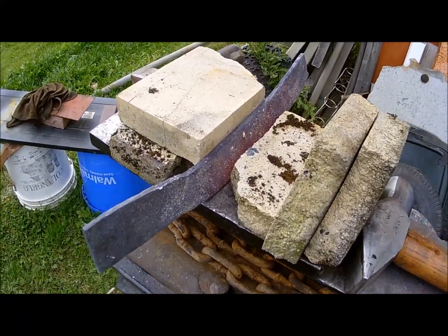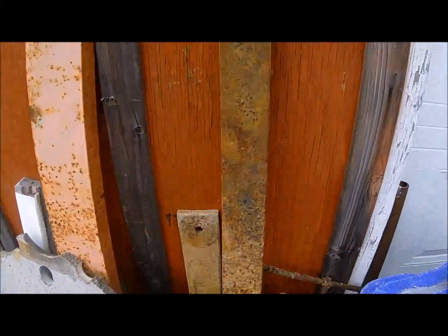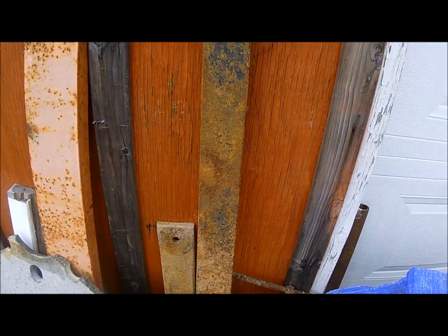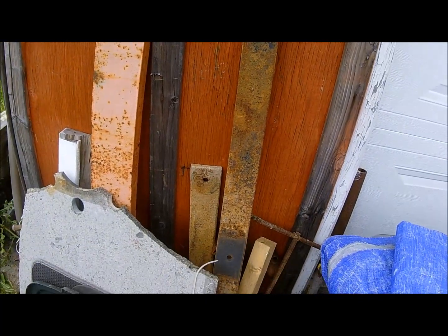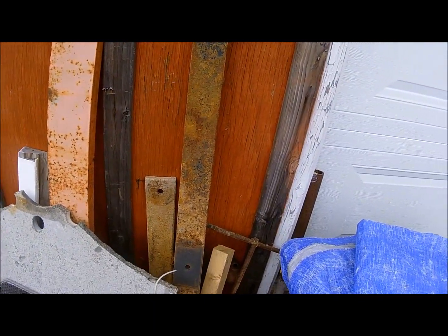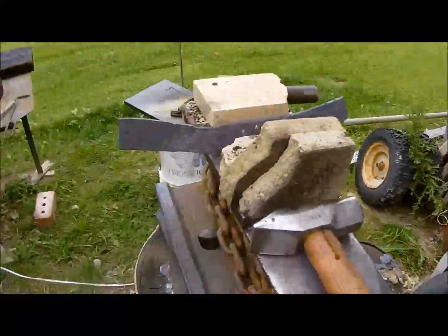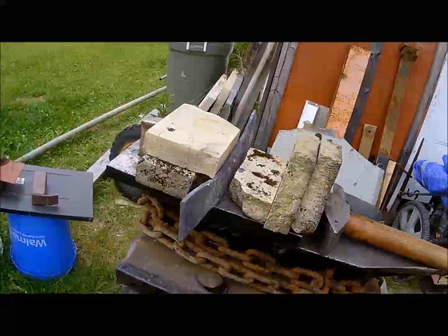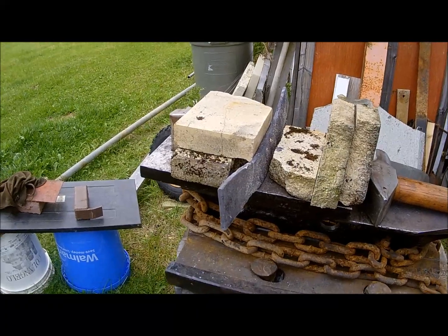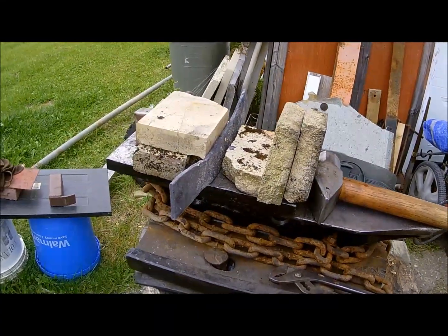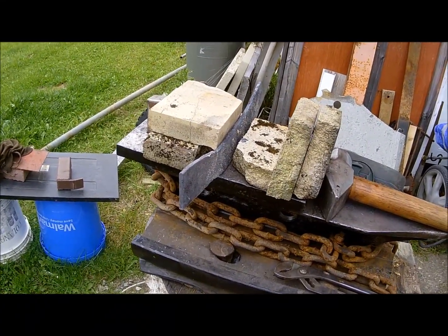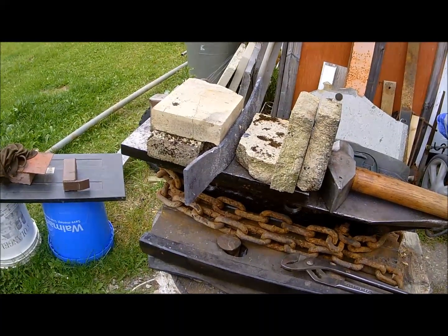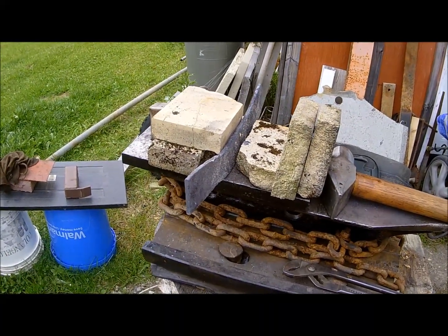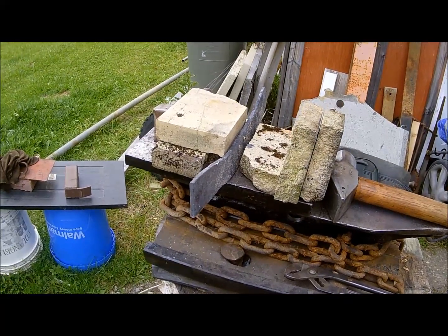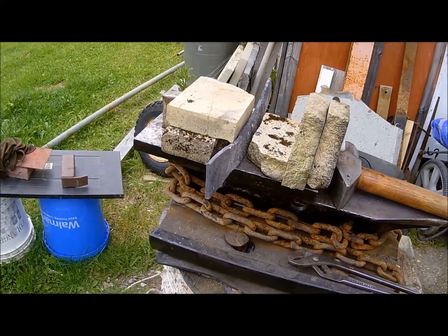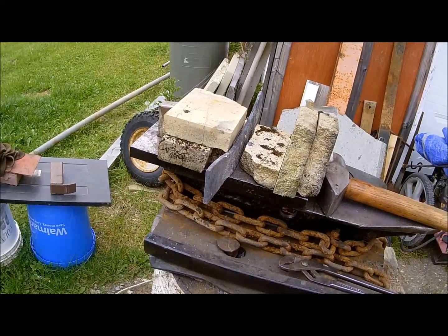When you take a piece of this spring steel and you pound and beat and heat it and heat it and heat it maybe 10 times to beat it into the shape you want, it's under a lot of stress. It went from being almost a ½ an inch thick to being approximately 3/16 of an inch thick, and it went from a piece that was about 1 inch wide and 8 inches long to a piece that's 2 inches wide and probably pretty close to a foot.